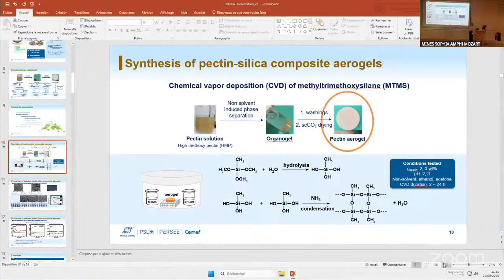No. Because there they saw that they could get the grafting, but when they did the supercritical drying after from methanol or ethanol, the acidic conditions in supercritical CO2 with ethanol basically led to the dissolution, like the bond was breaking, the silicon oxygen carbon bond. So they only could see it when they do the supercritical drying from another solvent like acetone, a non-protic solvent basically. So it could be the fact you don't see it in the end doesn't mean the grafting did not happen. It could be that the grafting had happened, but you've lost them during supercritical drying.